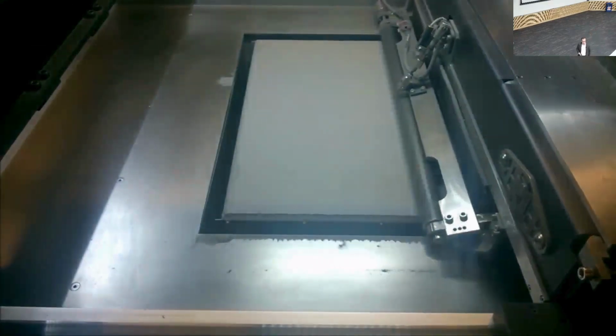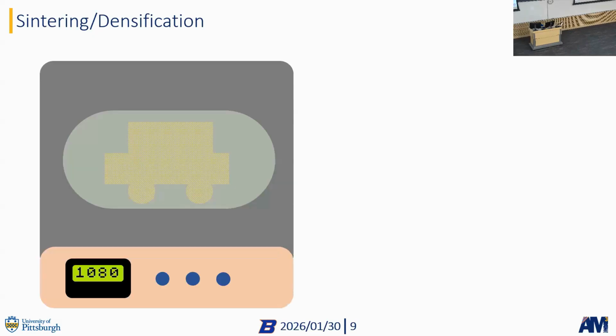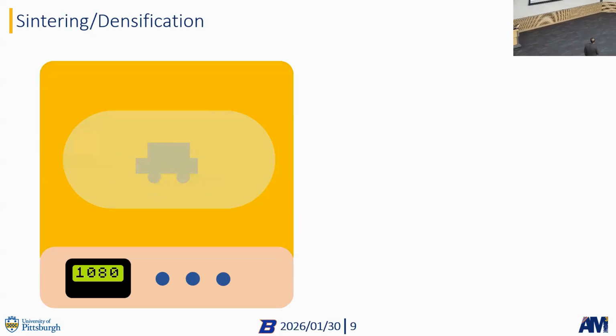and then need to do a high temperature heat treatment. This high temperature heat treatment is needed because after printing and curing, we have a part that's very chalk-like. So if you have this in your hands, you can actually rub off the powder. It is fairly stable. You can drop it from shallow heights, but the problem is it will just break if you put pressure on it, right? So in the high temperature heat treatment, we are applying a temperature that is fairly close to melting point. We densify our material. Since there's a lot of porosity in the as-printed part, it actually shrinks, right?